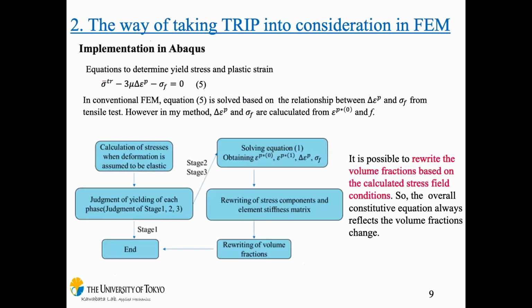So we incorporate this second method into the elastoplastic FEM. So firstly, we assume the matrix equivalent plastic strain, and we calculate the overall stress and strain using the second method. And finally, we check whether equation 5 is satisfied or not. And this calculation cycle repeats again and again until equation 5 is satisfied. And also it is possible to rewrite the volume fraction based on the calculated stress field and the plastic strain. So the overall constitutive equation always reflects the volume fraction. So this is the good point in this method.